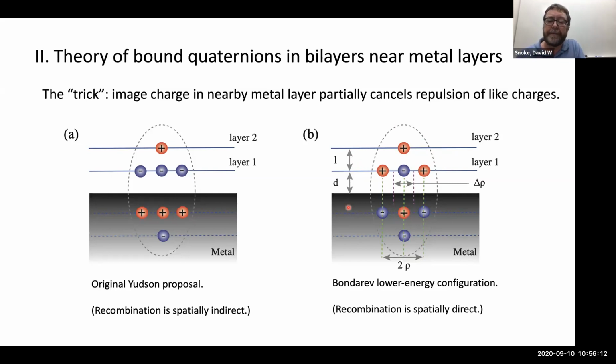So this becomes like 2 parameters that you can vary and see how this affects what you're predicting. Notice that the recombination in this would basically be sort of a renormalized indirect exciton. You'd have to have recombination between a hole and an electron between the two layers, so that would be spatially indirect. Whereas the recombination here, well, it could be indirect, but you have a much more probable recombination of a trion, basically an electron and a hole meeting in the same layer, which has a much larger oscillator strength. And so this becomes the dominant decay mechanism for these guys. Again, stop me with questions at any point.